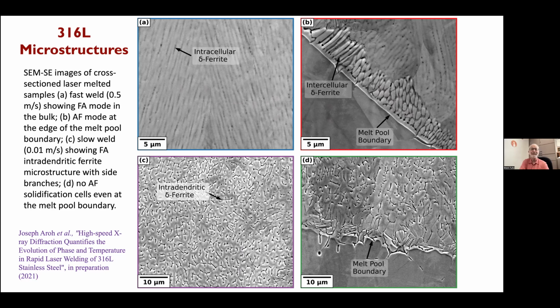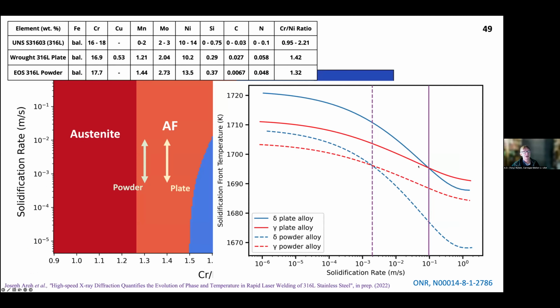Is there a simple rule of thumb? Well, we have not dived into trying to account for the microsegregation so much as just trying to understand the competition for which phase comes out first. I didn't include all of the evidence, apologize for that, but we have seen this transition. We do have the direct evidence from the diffraction experiments that if you go slowly enough in either of these compositions, you will see ferrite showing up first. But when you go fast enough, above some transition rate, and we're getting that about right, then the ferrite loses out and you get austenite coming out first, simply because the melting point suppression is less for the austenite as a function of speed.